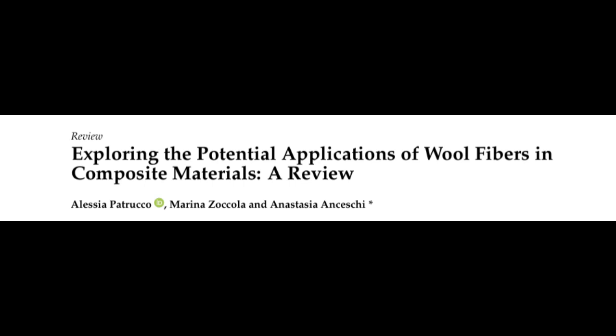So tricky. But there's been more promising work using a green pretreatment on the wool first, using superheated water hydrolysis. Superheated water? Yeah. It seems to break down the wool surface slightly, creating more compatible chemical groups, leading to better interaction with polypropylene and improved mechanical results. Even using finely ground wool powder, made by freeze milling, showed good dispersion and decent properties in polypropylene. So treatments and compatibilizers seem crucial for polymers.